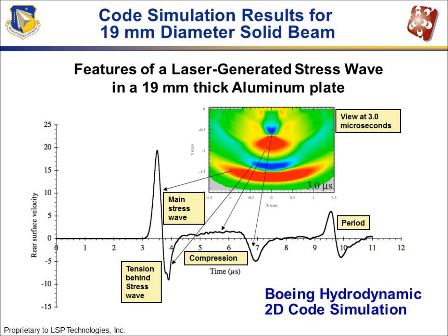Shown here is the XY dimension of a particular shot in time at 3 microsecond time points after producing the shock wave. You can see here that this is a moment in time in which the main compressive wave is close to the back surface. What is plotted here is the rear surface velocity as a function of time. The plot shows that the main stress wave hits a little after 3.4 microseconds, and there is the second tensile wave. Then there's a third compressive wave and a second tensile.